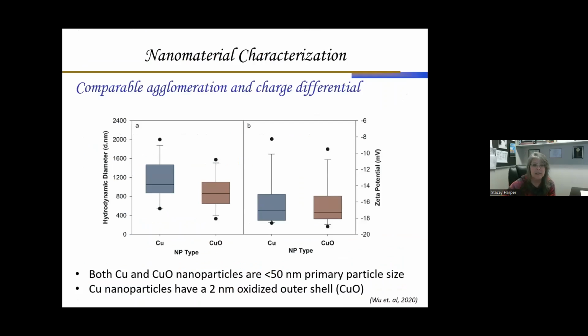And so what we see is the copper nanoparticles themselves, both the copper and the copper oxide. The primary particle size was about 50 nanometers, but you can see that they do agglomerate. Here's hydrodynamic diameter, but the agglomerates are relatively similar. And then these are just the zeta potential. And it should be noted that the outside of the copper nanoparticles do have a 2 nanometer oxidized outer shell. So the outermost surface is actually identical.